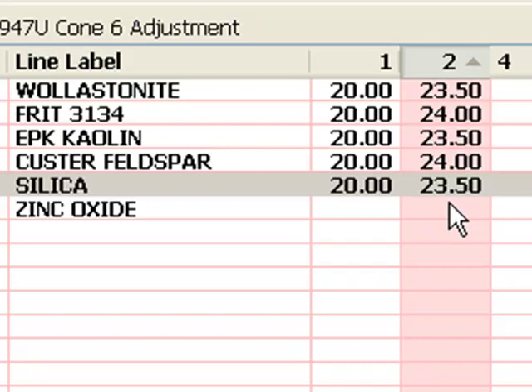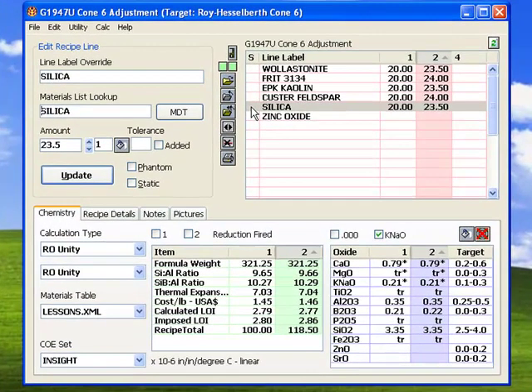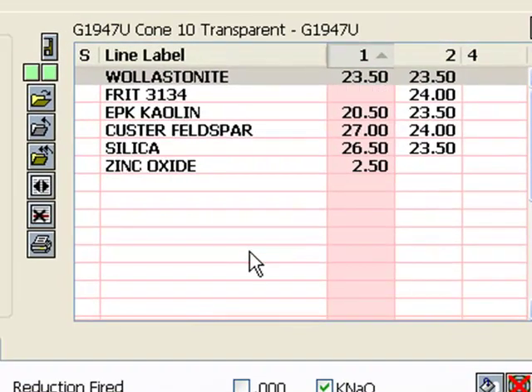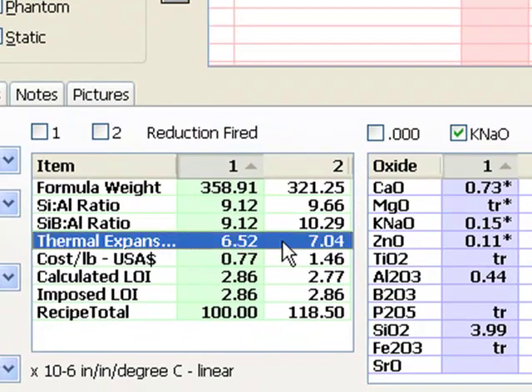The amazing thing is, I did not realize this until composing this lesson. When I open the original 1947U in Area 1 to compare, you would never know — they look quite different. The glaze on the left is the original; the one on the right is our adjustment to make it melt at Cone 6. Notice it raises the thermal expansion, but not by much. The more you adjust glaze chemistry to reduce the melting point, the more of a challenge it is to keep expansion and crazing down. The main reason is the lower silica and alumina, but the low-expansion boron is the secret to keeping the expansion down.